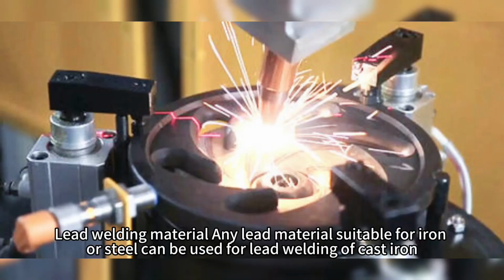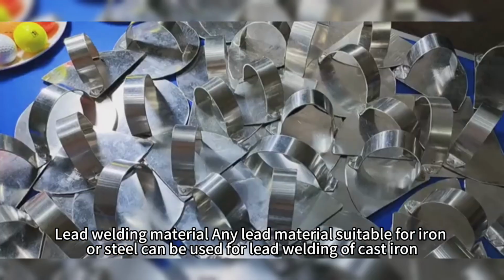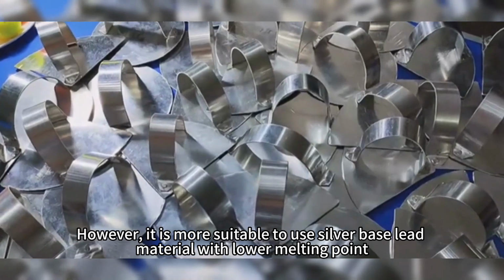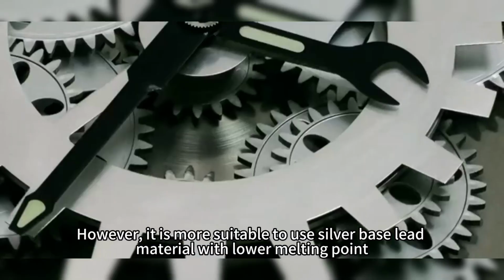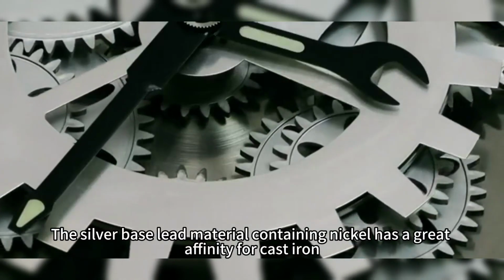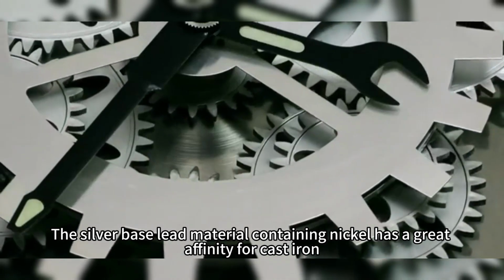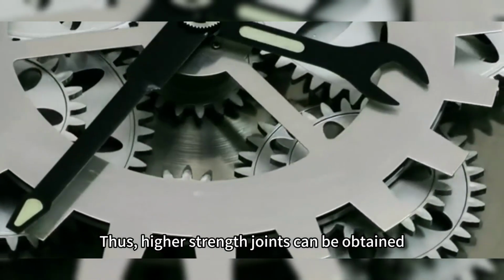Braze welding material. Any filler material suitable for iron or steel can be used for braze welding of cast iron. However, it is more suitable to use silver-based filler material with a lower melting point. The silver-based filler material containing nickel has a great affinity for cast iron. Thus, higher strength joints can be obtained.